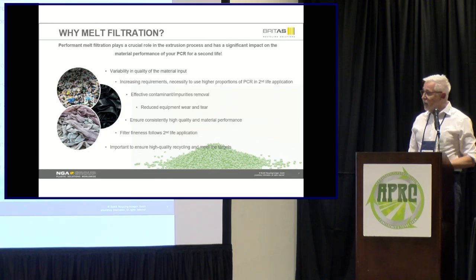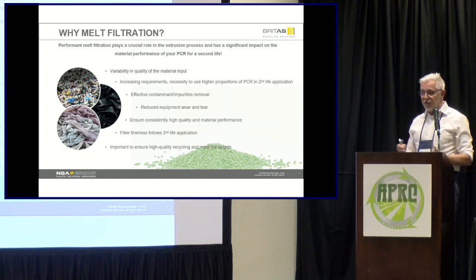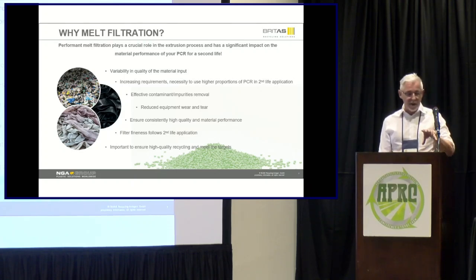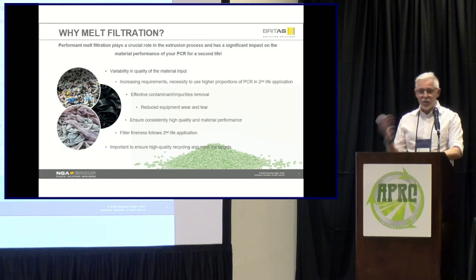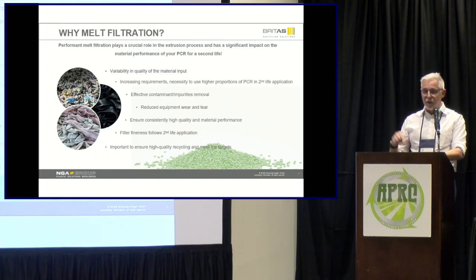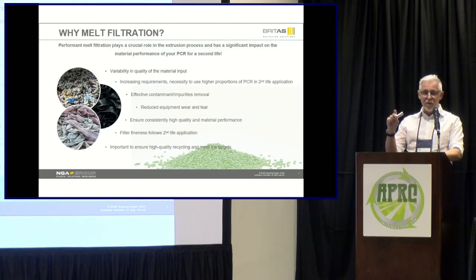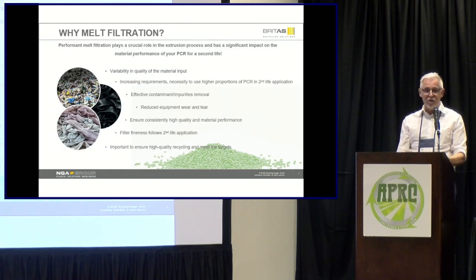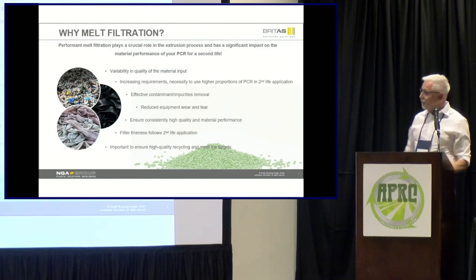It's important to bear in mind that the filter fineness, the technology, follows your demand. Why? Because it's a different effect. My second life application is blown film, 40 microns, 80 microns, or we are talking about thin wall pipe extrusion, thick wall pipe extrusion. Could be filter fineness is 70 or 60 microns, or I can use 300 or 400. And at the end, you meet your targets, your quality targets, or the targets of your customer.